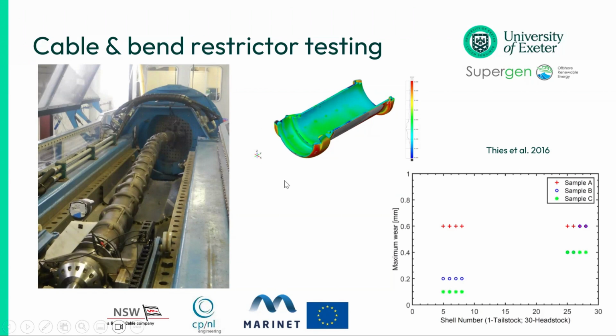One specific task here was that they had different suppliers for those shells. So we had a 3D scan before, we tested them, and a 3D scan afterwards, for us to work out what the wear is at different positions in that string, but also how the different suppliers compare.